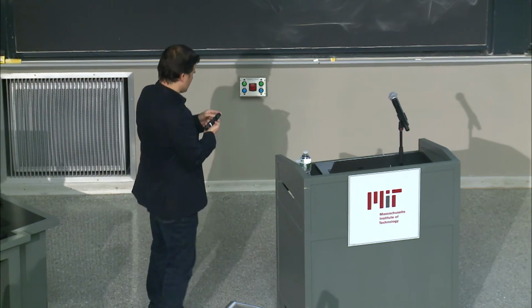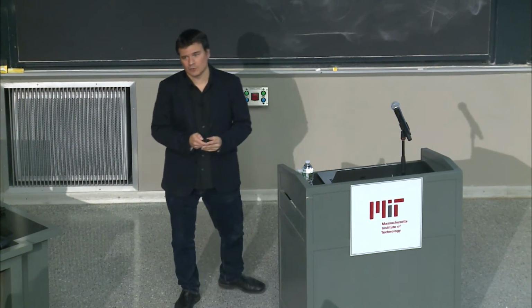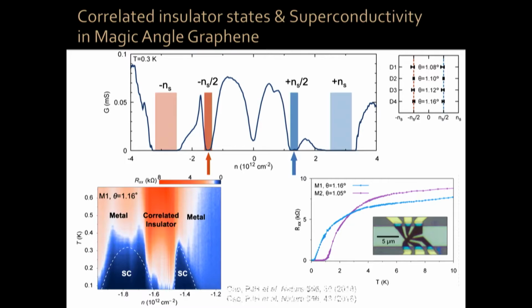when you make these type of devices, okay, then the magic sort of starts to happen, and what my group discovered in 2018 is that when you make these devices at that particular twist angle of 1.1 degree, and it's important that it's 1.1 plus minus 0.1 degree. That's the margin of error that you have, roughly, okay? And you charge this system with electrons at a certain doping density, in particular, 2 electrons or 2 holes per moire unit cell, so it's a tiny density of electrons. The system, which is made out of 2 pieces of the best conductor in the world, graphene, becomes an insulator, okay, a correlated insulator.